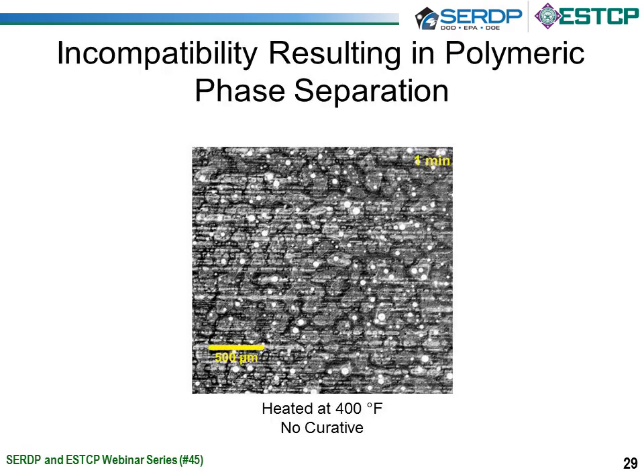Slide 29, in order to prove this concept, we took the high OH and the low OH and wanted to demonstrate that those two polyols, when combined with no curative, would demonstrate phase separation upon heating. We took the high and low OH polyol in a 1-to-1 ratio. We co-extruded it, ground it, and sieved it to a uniform particle size of less than 100 microns. We electrostatically applied it to Q panels as one would a typical powder coating, with the objective to show that the high and low OH without the curative would phase separate. We heated for 1 minute at 400 degrees Fahrenheit, and then quenched it by placing it upon a cold surface. This optical image shows that phase separation did occur in as little as 1 minute.